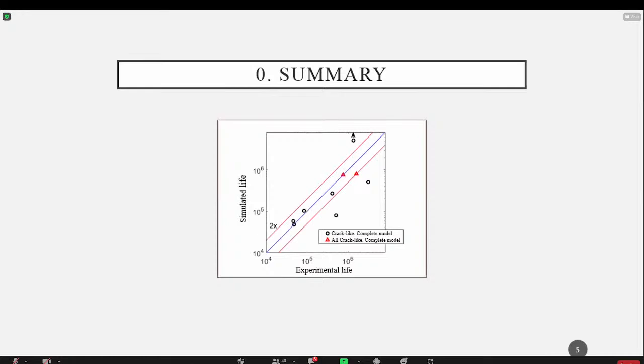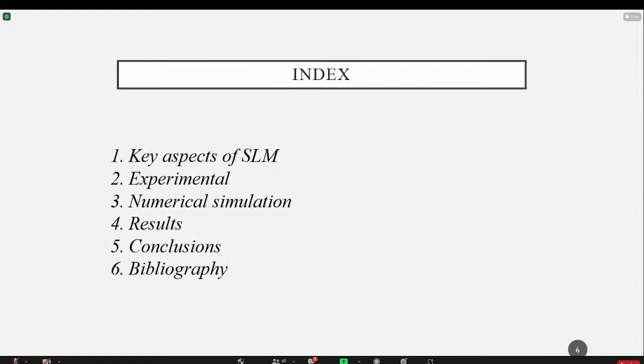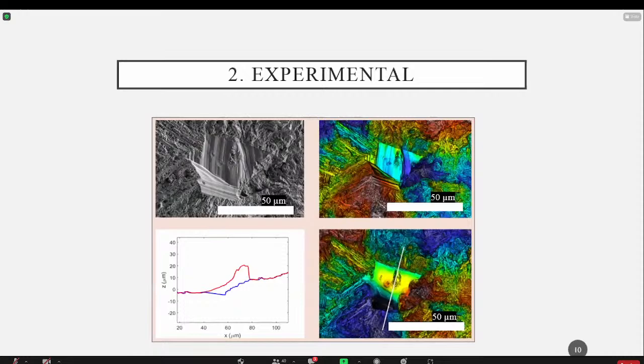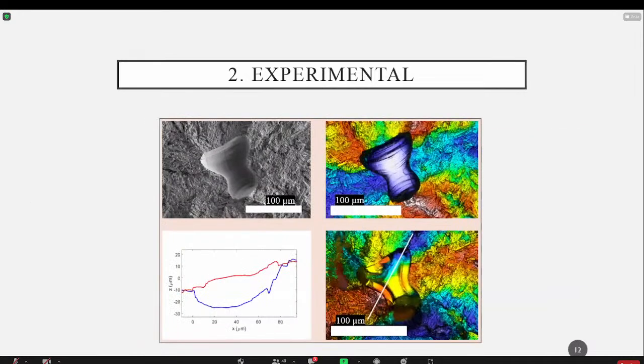The defect that you had in your material was a lack of fusion defect. And this type of defect has a high aspect ratio, being more planar rather than spherical. Do you think in the case of spherical defects, you would also get the same range of accuracy from the simplification of a crack-like defect or not? Yes, indeed. I can show you a few more examples, because this is the example we saw right now, but I brought you here another one. Okay.